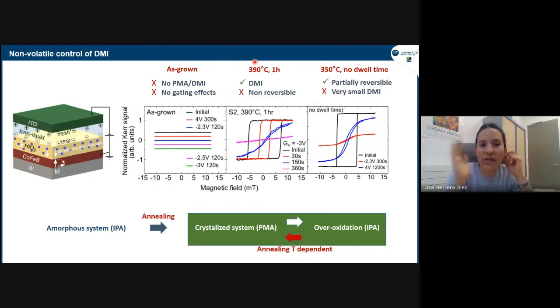So then we said, well, maybe we can find a compromise. Let's anneal, but at a lower temperature. And this is what we did here. It is partially reversible, so it goes in the right direction because it's probably just partially crystallized, but we get almost negligible DMI. So what we learned from this is that if the system needs to be annealed, then we're probably going to lose in terms of magneto-ionic efficiency. I think that's an important message, especially for these tungsten systems where we need this annealing to get very nice magnetic properties like strong DMI and strong PMA.